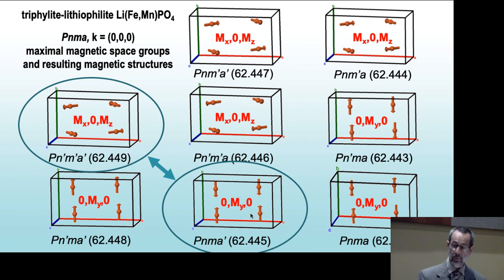So if you look at the observed magnetic space groups that correspond to the ordered structures for triphylite and lithiophyllite, these two occur. A little bit of iron stabilizes the moments in this direction with just an MY component, and then the manganese end member has both an MX and MZ component, but realizes only an MX component. So the magnetic phase diagram for this solid solution has two phases.